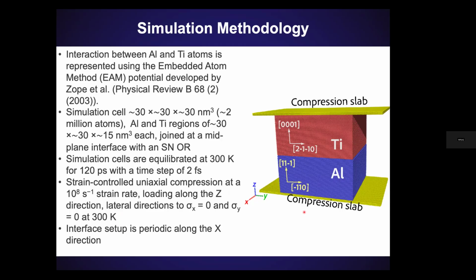But when you do molecular dynamics simulations, you need to pick an interatomic potential that is actually realistic and can reproduce the properties of the material. So we used an embedded atom method potential for aluminum and titanium. Our cell was a 30 by 30 by 30 nanometer cube.